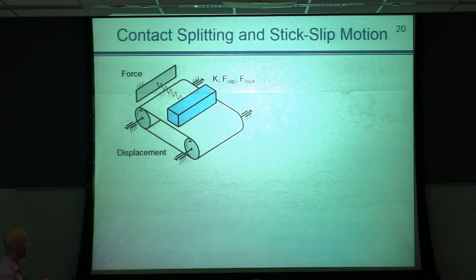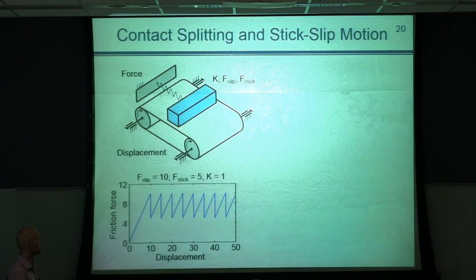So what you see here is a body that is placed on a moving conveyor, and this massless block is connected with a spring to the wall. The three parameters that we changed here are spring stiffness and kinetic and static friction at the interfaces. So when the conveyor starts moving, the block sits on the surface due to static friction and moves together with it, and the spring is loaded. When the elastic force becomes larger than the static friction, the block moves back until kinetic friction is achieved, and then the process is repeated again.